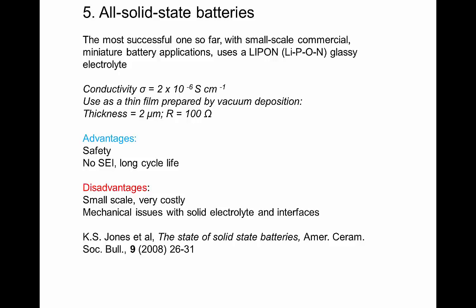And there is one small scale commercial example of a solid state lithium battery using a lithium phosphorus oxynitride glassy electrolyte. Its conductivity is not particularly high, but it's used as a thin film, and so the actual resistance of the electrolyte is quite small, with a thickness of 2 micrometers of the electrolyte. Its resistance is 100 ohms, and so it's feasible to use that in a battery.